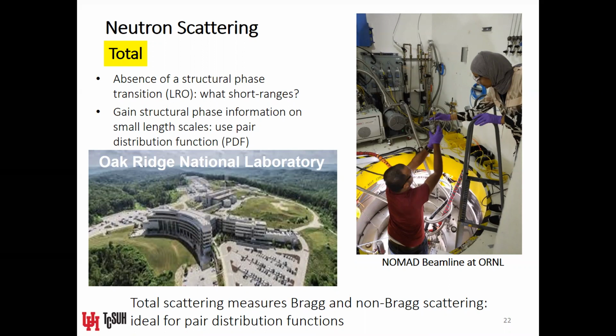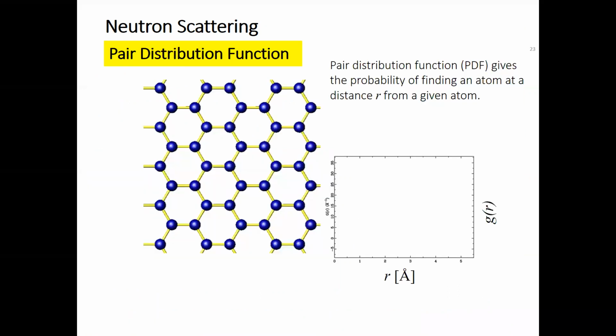In pair distribution function analysis, what you want is scattering over as large a Q range or angular range as you can get, so that you can ultimately convert that scattering vector information into information about the small distances, or the real space distances, between atoms. You collect a broad range of both Bragg peaks and non-Bragg scattering in order to form a pair distribution function. And that is essentially a probability distribution for finding an atom at a given distance from some reference point.